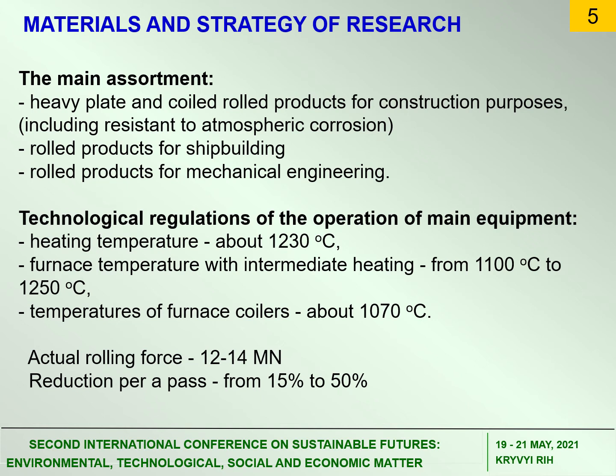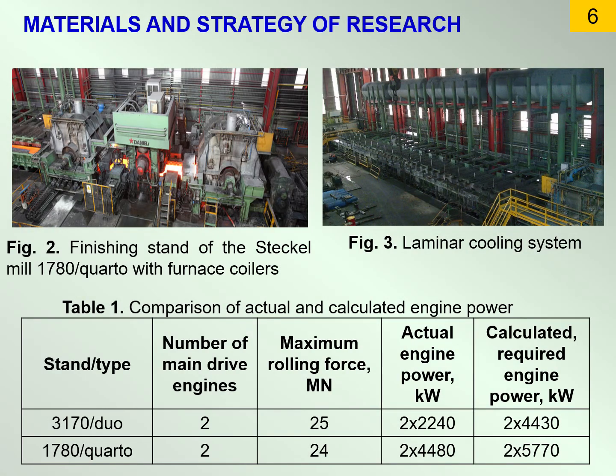It should be noted that at these temperatures there is a significant reserve of energy-power parameters. The actual rolling force in roughing and finishing stands is in the range of 12 to 14 meganewtons, with a reduction per pass from 15% to 50% according to the assortment, which makes possible further development of technology and expansion of the assortment. In figure 2, the finishing stand of the Steckel mill 1780/quarto with furnace coilers, and in figure 3 the laminar cooling system are shown.